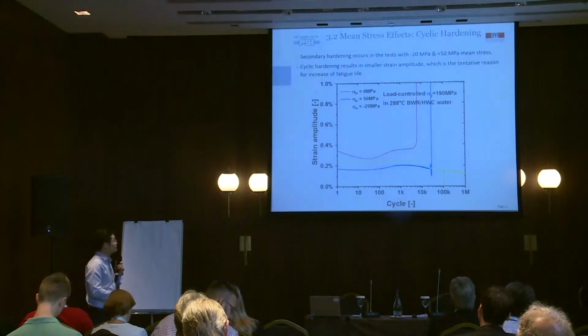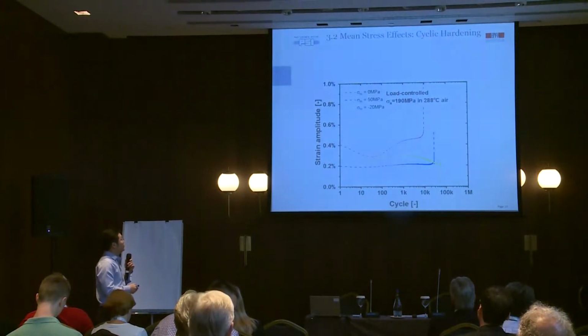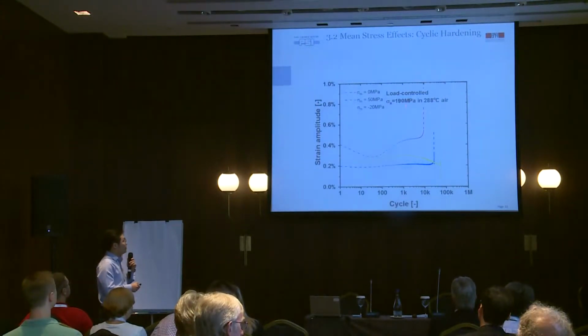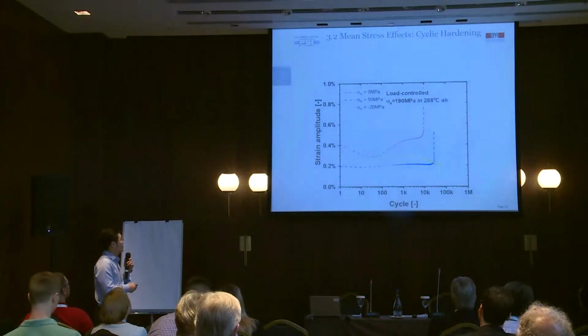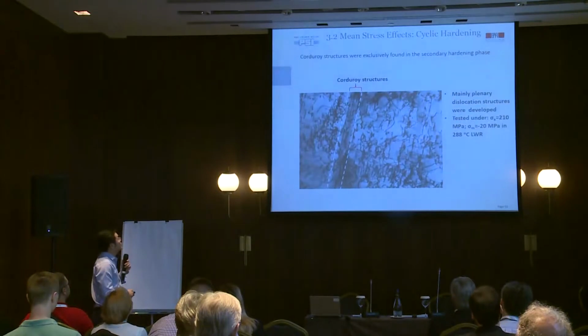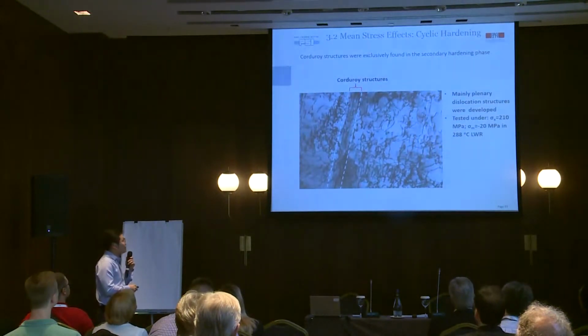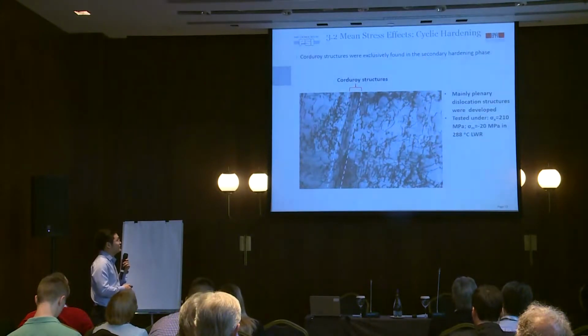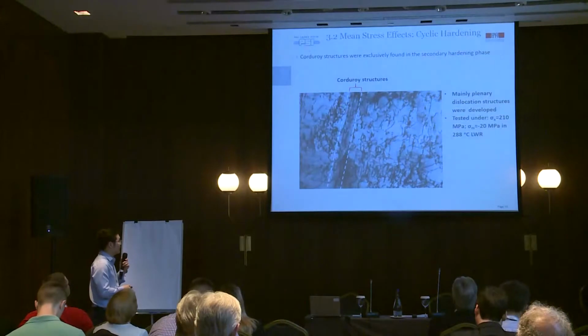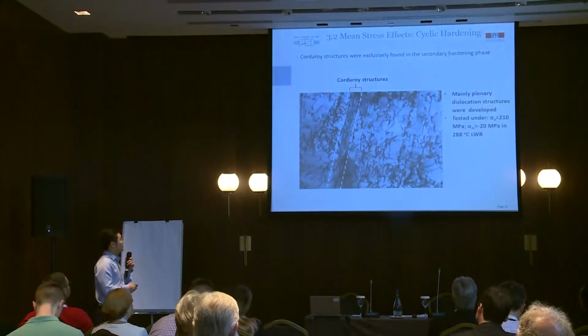life. And this is also an example with a stress amplitude of 190 MPa in air. It also has a similar strain evolution in the air condition. So we want to have a more in-depth understanding of the mechanism of the mean stress effect, about the second hardening. So we cut the specimen after the test to check in the TEM, in the EBSD, and in the ECCI.